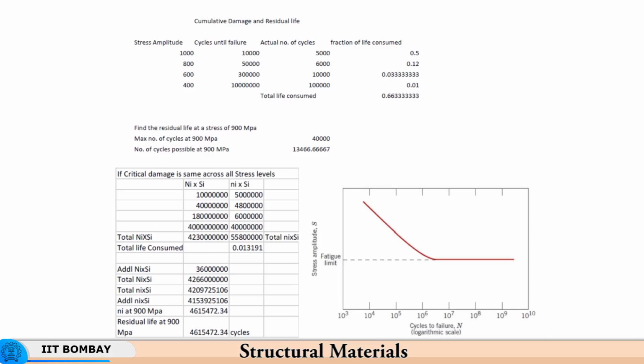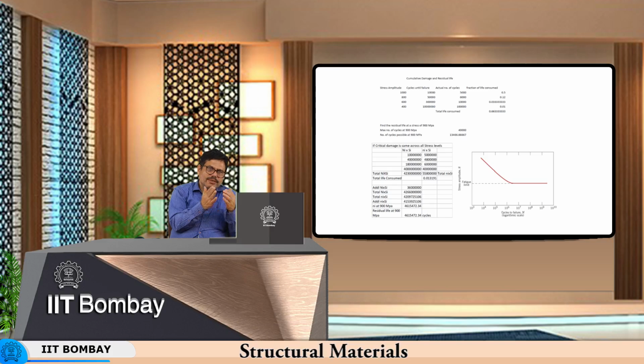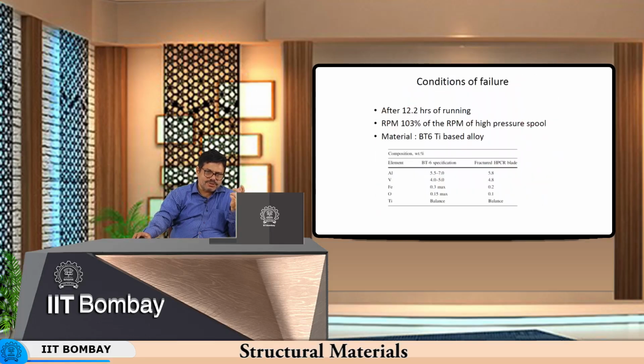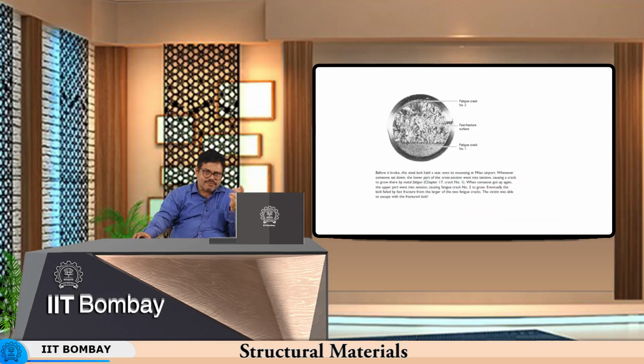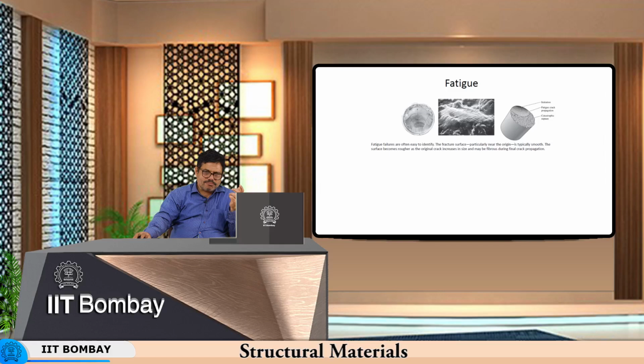How does the crack propagate with number of cycles? So, I told you that you see striations, evidence that the crack has propagated by a very small distance in every cycle. So, the damage which has been done by each cycle is recorded in the form of striations on the surface of the fracture. And then once the cross section left is relatively small, then you have fast fracture, because now there is nothing to arrest rapid propagation of the crack. So, that is what we call fast fracture, and that is what we saw in one of the pictures we were studying earlier, for example here. So, here you have initiation, fatigue crack propagation, and region of fast fracture.